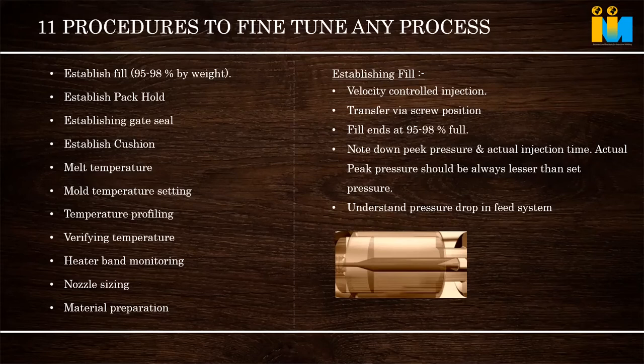Why? Because we cannot fill 100%, since it can flash out. That's why we say 95 to 98%. We have to fill it in the injection phase. If we are filling too slowly, what happens? The melt temperature can drop, or we fill only 80% in injection and switch to holding. So there is a micro stoppage happening, known as the switchover phase.